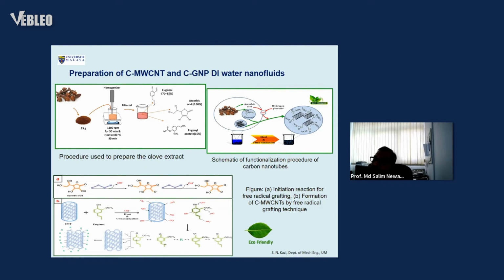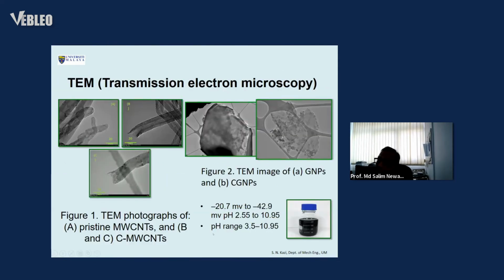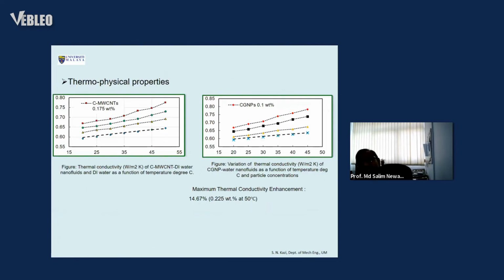So it goes from hydrophobic to hydrophilic with the addition of the OH, the reaction being shown here. And then another method is adding surfactant. If the surfactant is added, we get problems there: it reduces the conductivity. So we can see that, due to these functionalized carbon structured nanoparticles, we get a higher heat transfer coefficient,